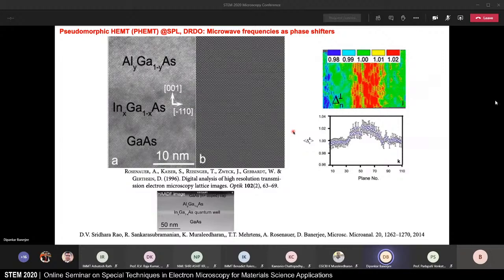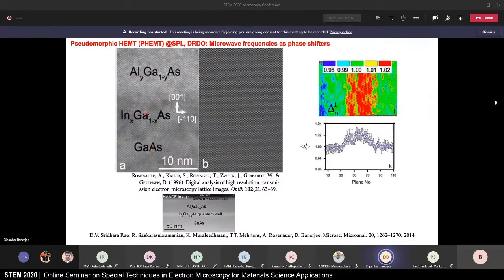And I'm going to show you some slightly different aspects of this work. So this is high resolution electron microscopy of the gallium arsenide, indium gallium arsenide, and aluminum gallium arsenide structure. And the technology problem is to control this composition here such that you get the kind of band gap that you want. And you have to control the composition and therefore the strain in the material.